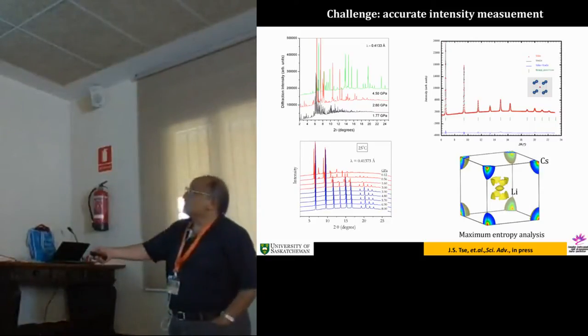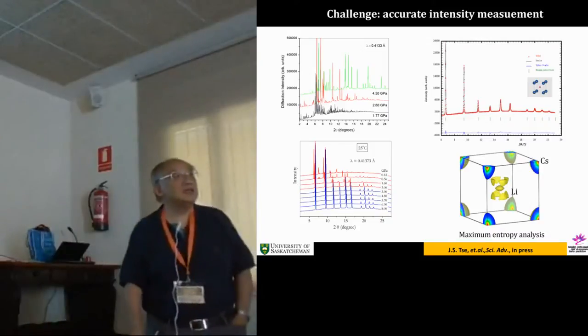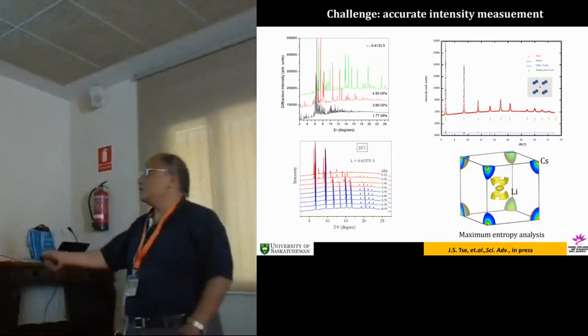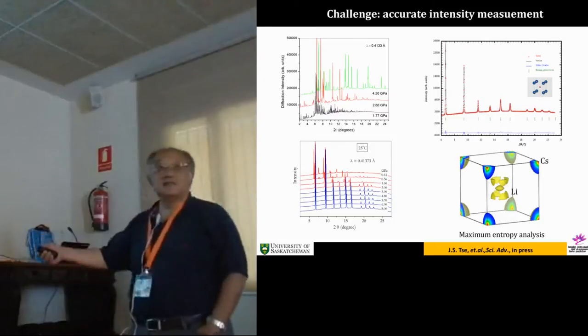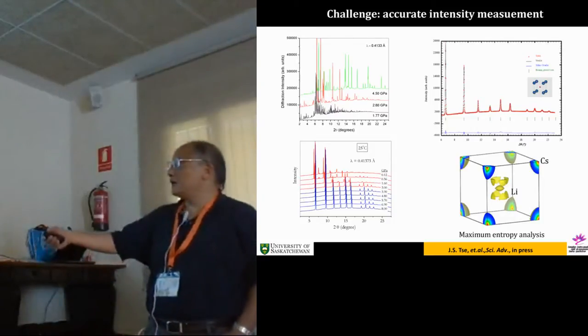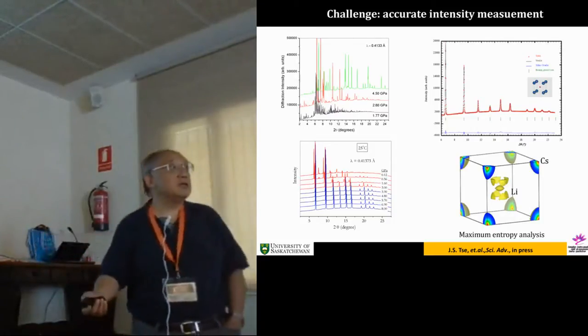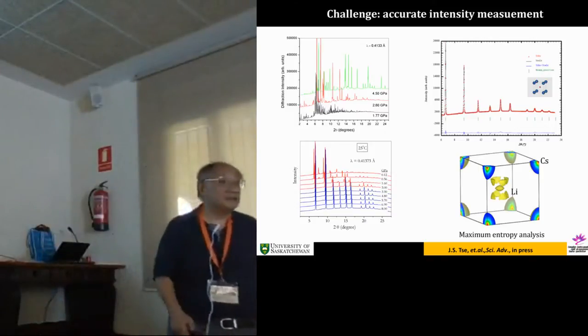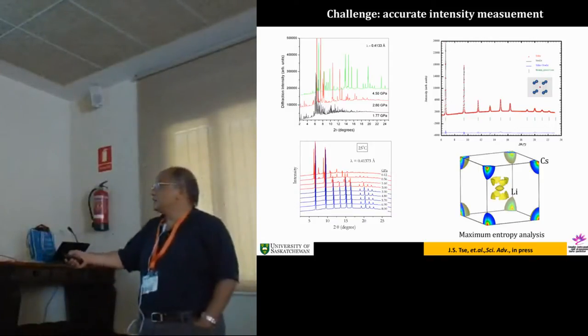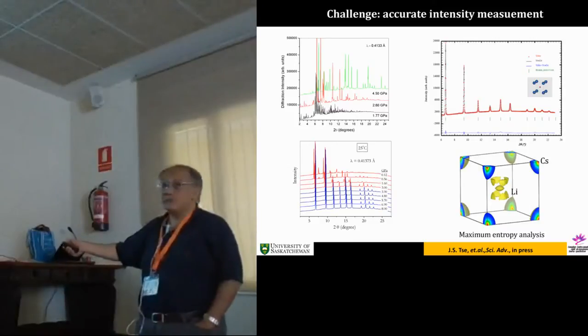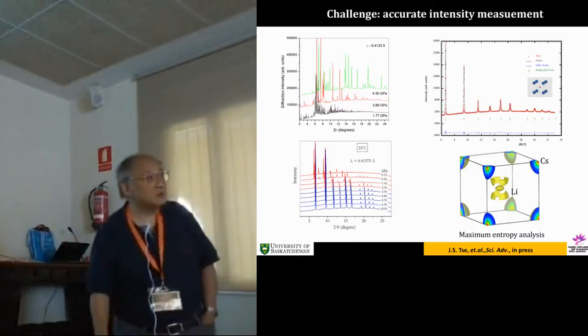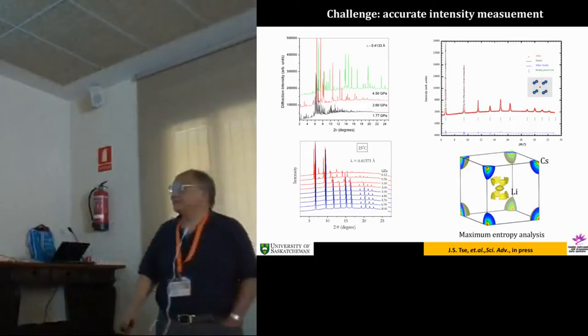Look at this pressure here, it's 1.77 GPa. So if you put lithium and cesium together, just close the cell, you already have many peaks. It's showing me this is a mixed phase of alloys. We were lucky that we have roughly 50-50. We proportioned, and we got a very well-defined diffraction pattern. You don't know that it's cubic right away, primitive cubic.